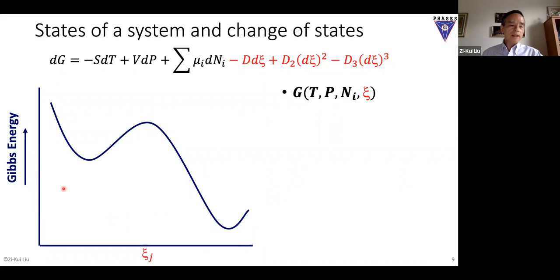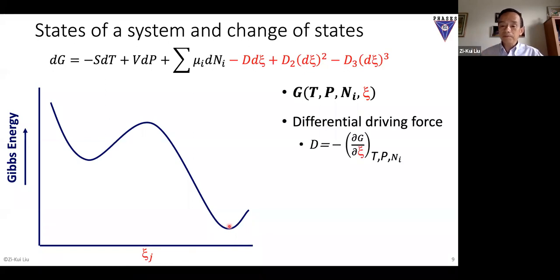So what does it mean? So talk about Gibbs energy, a function of state, right? For example, take water as an example again. You have ice, you have water, but at minus 10 degrees, okay? So now you can see you have a fraction. At the beginning, you have 100% of water, and then as time goes, it will change to 100% of ice because ice has low energy. Okay, so you can talk about driving force. You can have differential driving force. So any moment when the water becomes ice, there's a driving force for that.